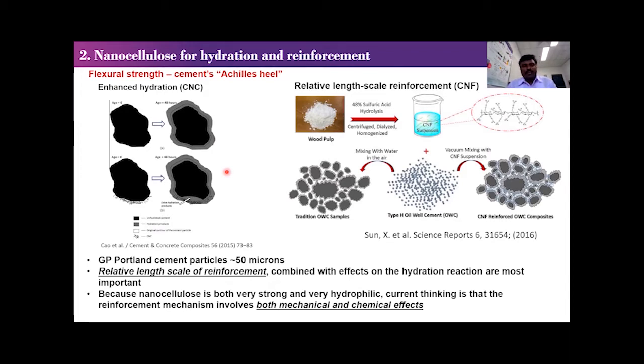This research on adding nanocellulose into cement has been going for a few years now, and there are two types of mechanisms involved in improving the properties. What you're seeing here, the black particle is the dry cement particle. You can add nanocellulose that goes on the surface of the particle, and when you add water, it can act as a network for water penetration and further hydration. The gray area is the hydrated area. That is what gives us the strength and the adhesive property that can hold the whole aggregate you are adding, sand and stones. So we want to enhance that hydration.